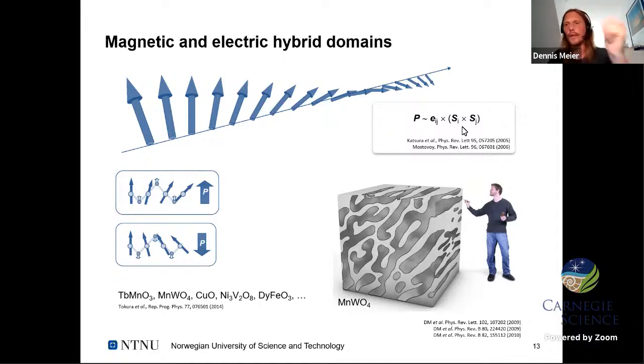And this also holds at the level of the domain. So we have hybrid domains with ferroelectric and magnetic order correlated in a one-to-one fashion. So playing with one will also necessarily affect the other. A system where this was discussed in the beginning extensively was terbium manganite, but nowadays we know that this mechanism is really all around. We have it in manganese tungstate, cupric oxide, nickel vanadate, and this list is really very, very long. And it's not a quite unusual mechanism. You can find it in a lot of magnetic materials that have low enough symmetry.